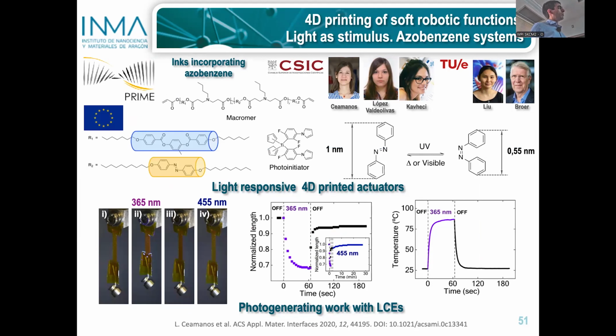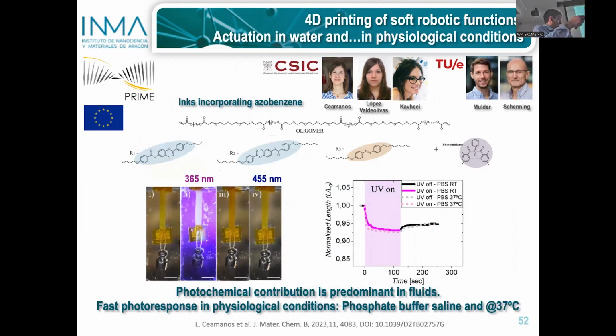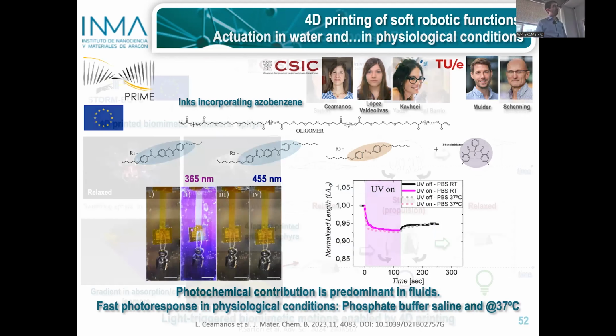But when you remove the UV light, you get to a level that is different from the initial one, and this level is due to the presence of these molecules that disturb the order in the liquid crystal. This is checked by immersing the system in water. In this work we did it. You put this in water, so the heat is taken by the water. So the photo-induced heating is almost negligible, and almost everything that you see is due to this photochemical component.